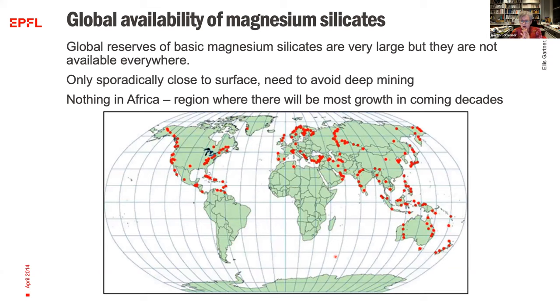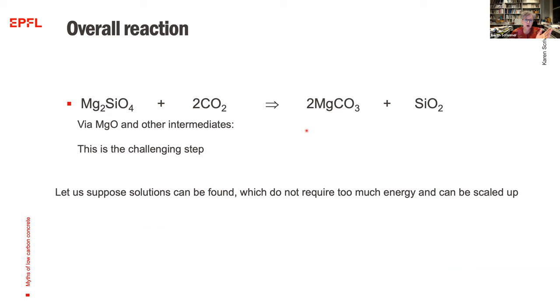So this map here shows the distribution of magnesium silicates. You can see they're really occurring at plate boundaries, because there's a lot of magnesium silicate in the magma, which is thrust up by, again, volcanic action at plate boundaries. And here you can see quite easily that, for example, if we take Africa, where there's going to be most increase in demand, there's no supply of magnesium silicates, so you would have to put in place very important transportation costs to get the magnesium silicates here. There's a lot up here in the north of Europe, but there's not many people there, so not much demand for cement. Then you've got to have your reaction.